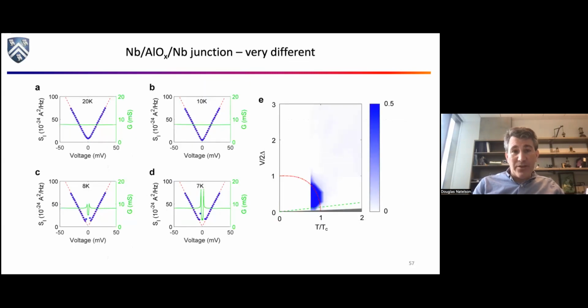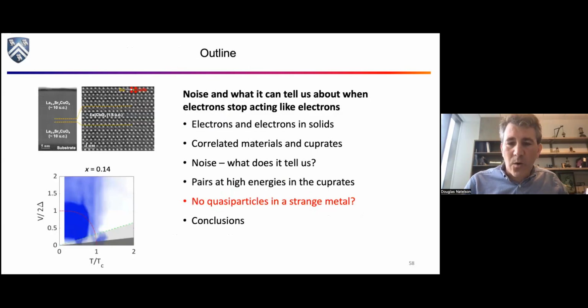Now, a control experiment: you could do the same experiment in a conventional superconductor, right? So we did the same kind of measurements in niobium, a commercially purchased niobium junction. And you can see in that plot, we couldn't get that cold for various reasons, but basically, it doesn't look like those other things at all, right? You basically never see that enhanced noise at high biases or at high temperatures in the conventional superconductor case. So that was pretty cool.